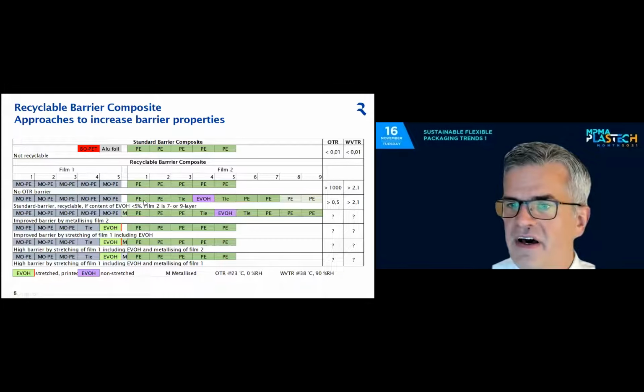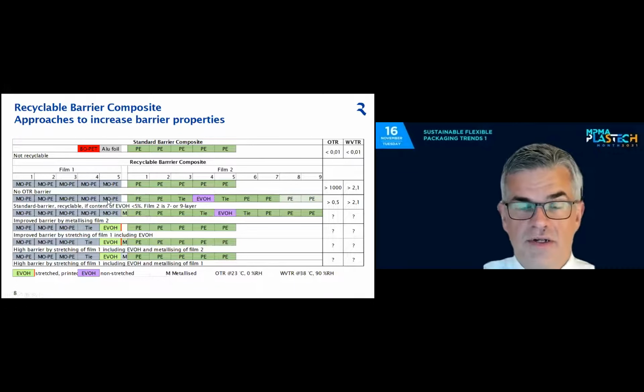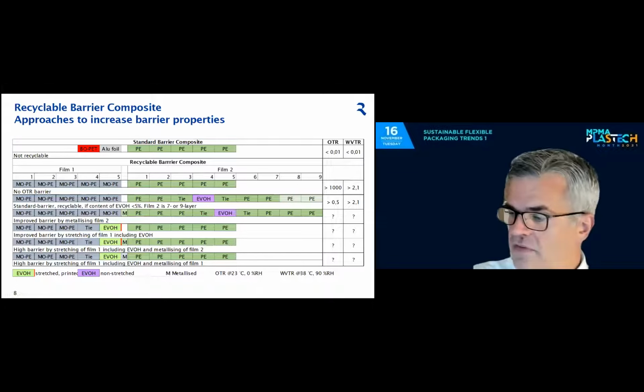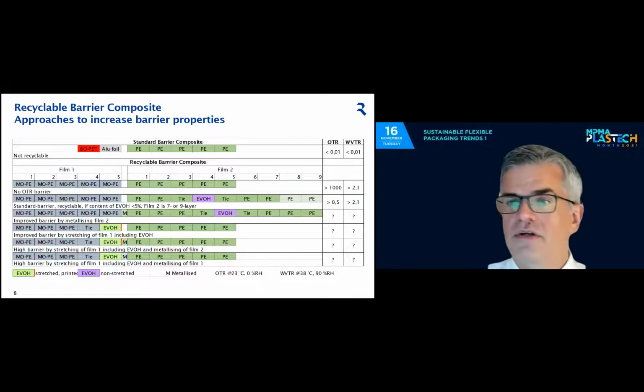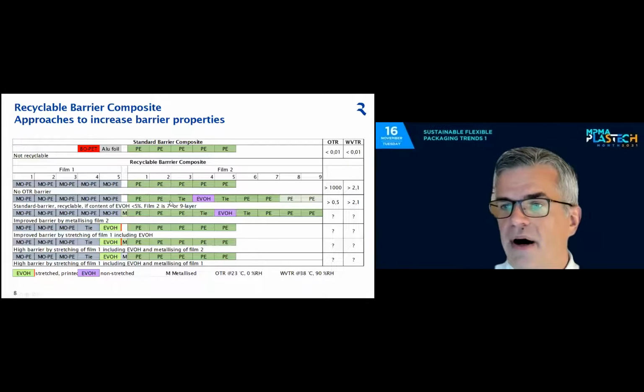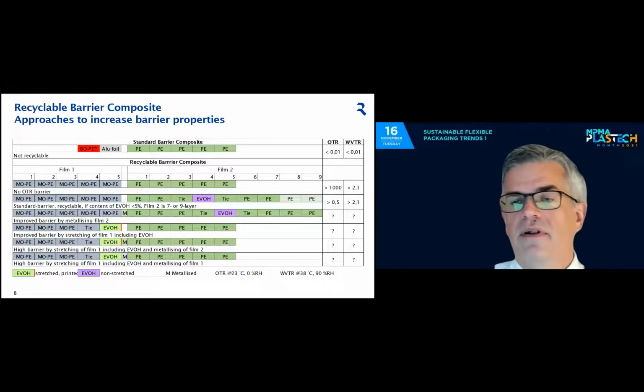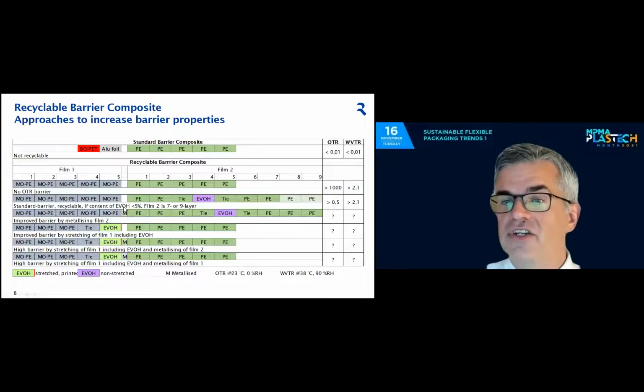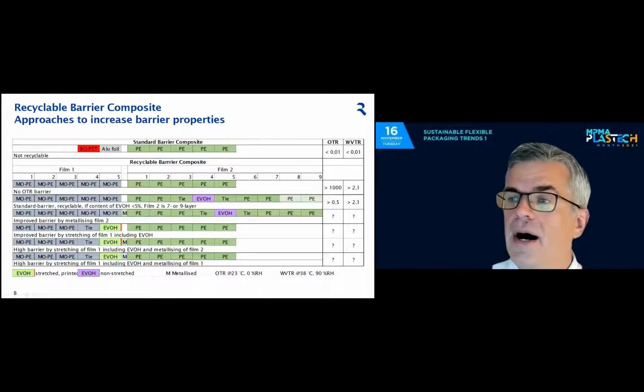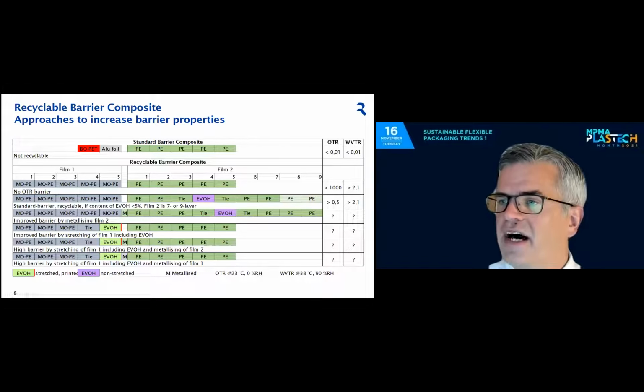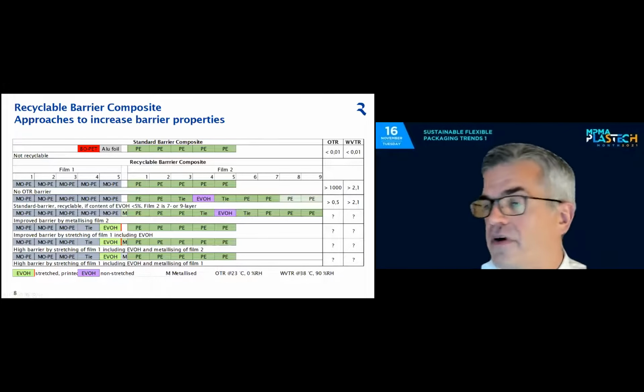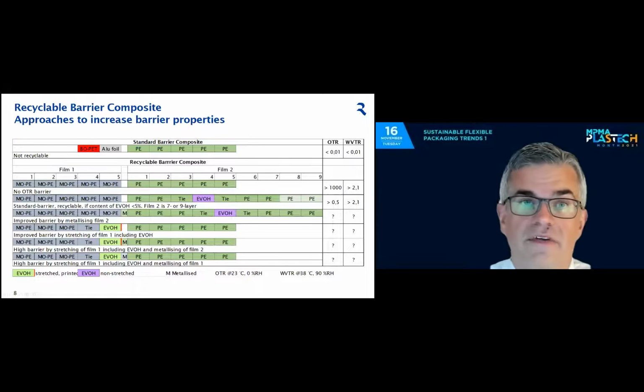Film 2 is a 7 or 9 layer film. Film 1 is still stretched PE film for the strength, for the stiffness of the pouch. Barrier properties are realized by my lamination film, by the EVOH. We can call it recyclable if the content of EVOH is well below 5% in this laminate. And then we can create oxygen and water vapor transmission rates around 0.5 and 2.1 respectively.